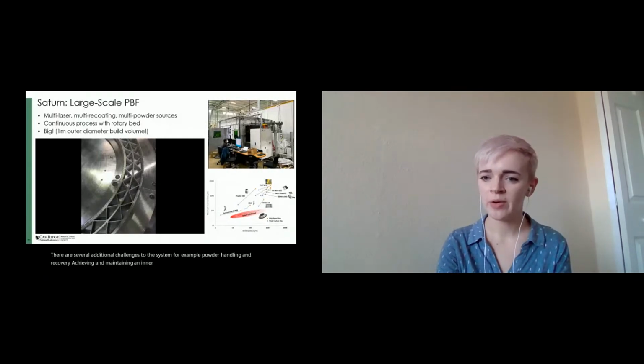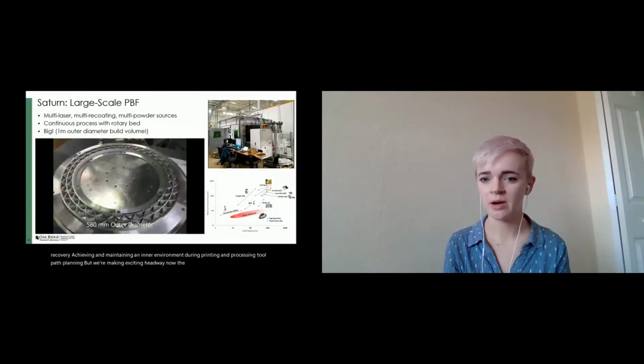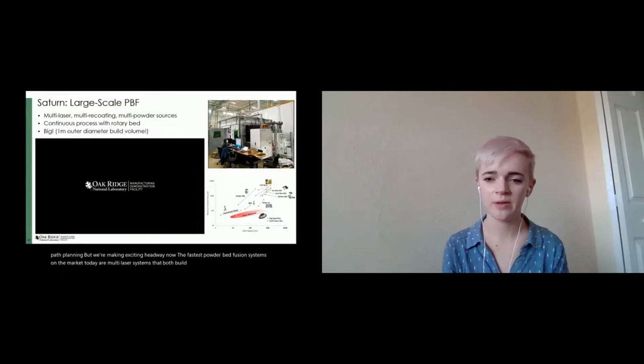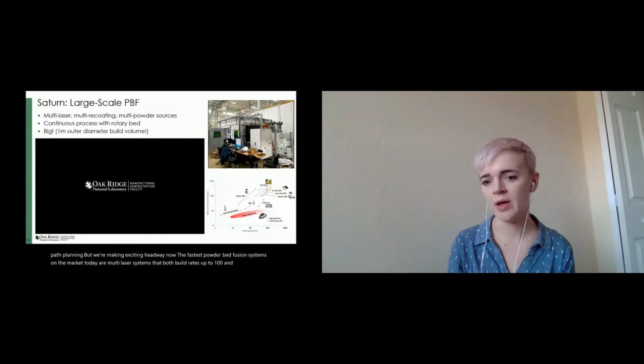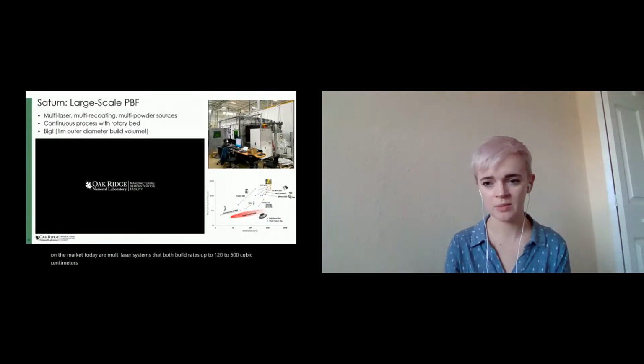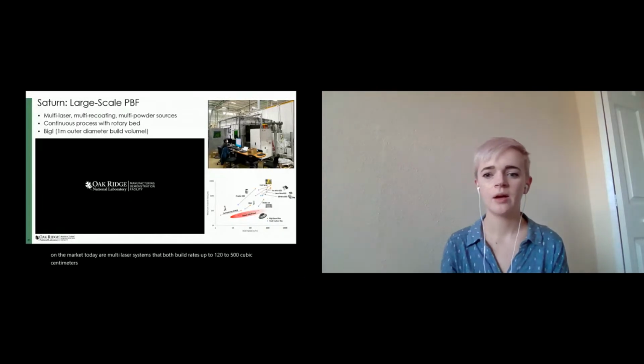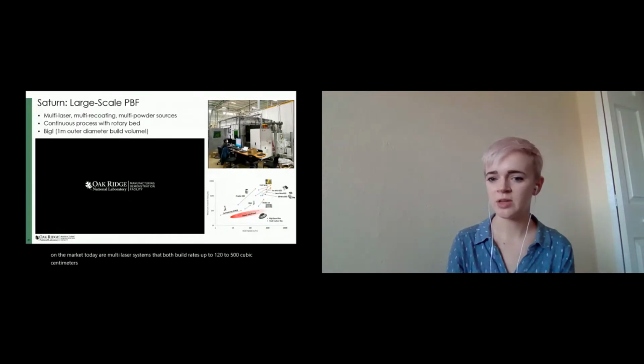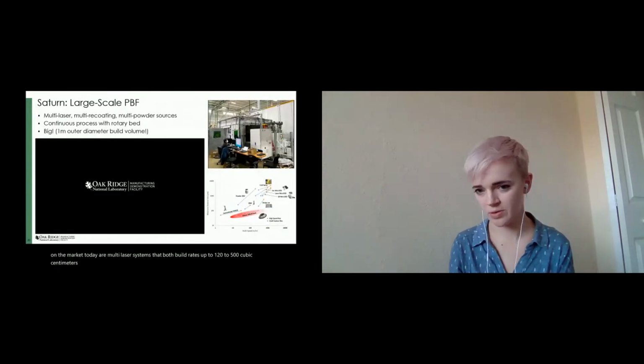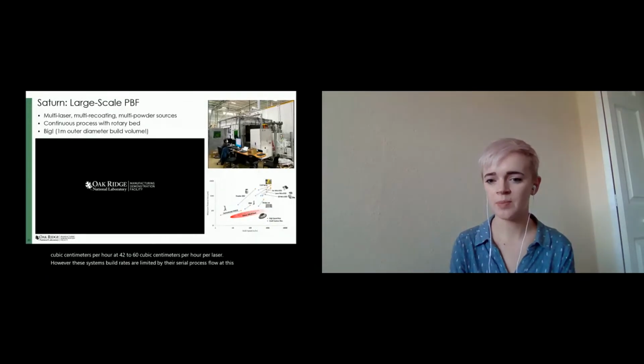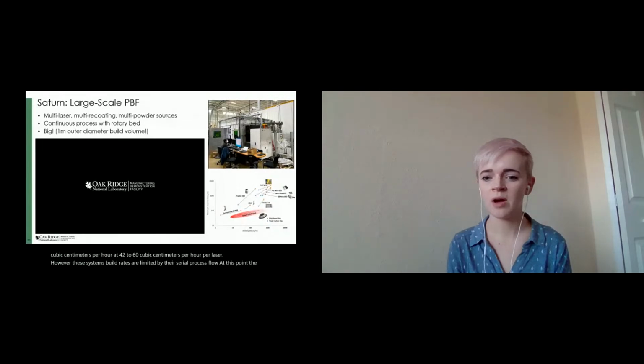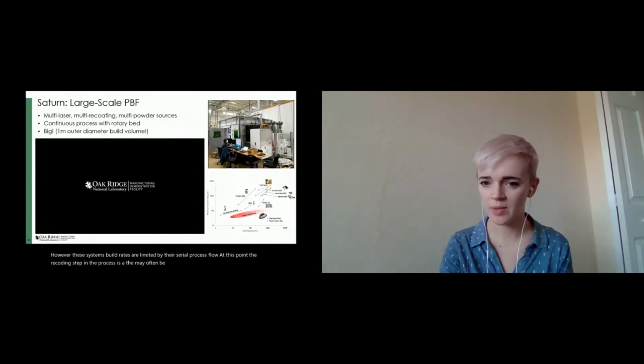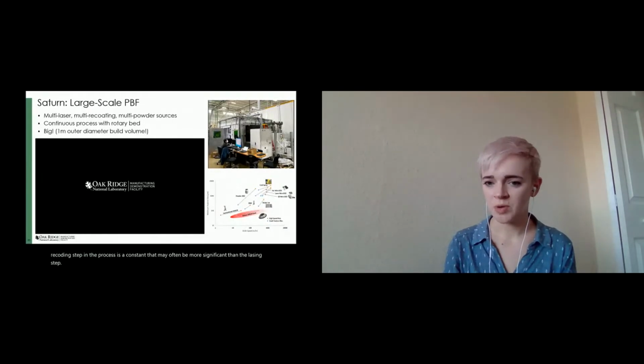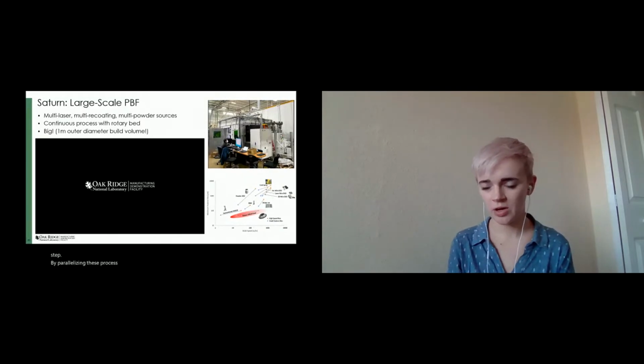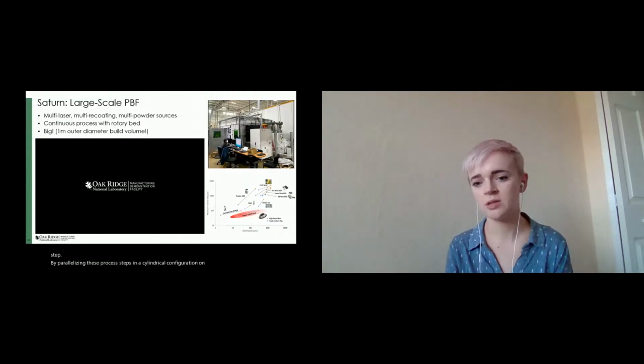Now, the fastest powder bed fusion systems on the market today are multi-laser systems that boast build rates up to 120 to 500 cubic centimeters per hour at 42 to 60 cubic centimeters per hour per laser. However, these systems' build rates are limited by their serial process flow. At this point, the recoating step in the process is a constant that may often be more significant than the lasing step.